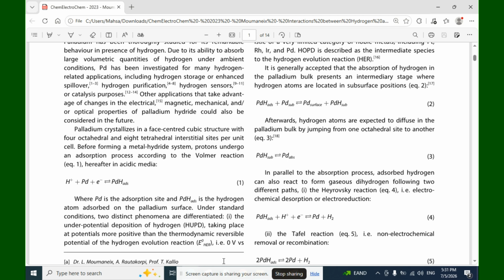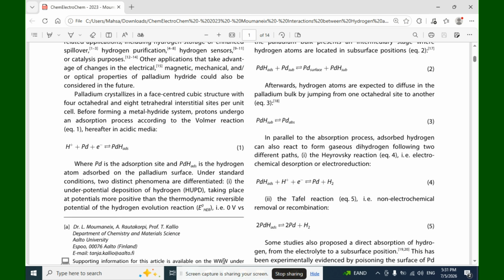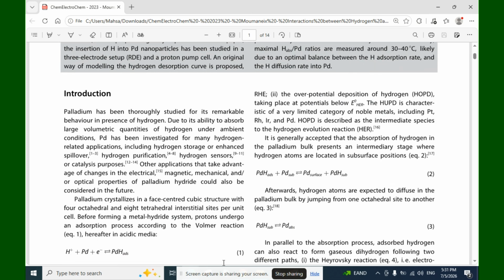Under standard conditions, two distinct phenomena are differentiated. The first one is the underpotential deposition of hydrogen, taking place at potentials more positive than the thermodynamic reversible potential of the hydrogen evolution reaction, for example, 0 volt versus RHE. The second one is the overpotential deposition of hydrogen, taking place at potentials below HER. The HUPD is characteristic of a very limited category of noble metals, including platinum, rhodium, iridium, and palladium. HOPD is described as the intermediate species to the hydrogen evolution reaction.